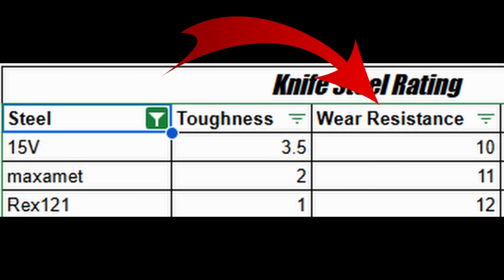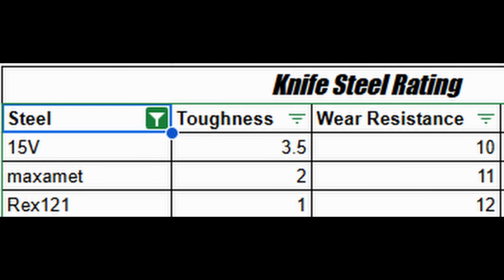Dr. Larrin Thomas doesn't have many steels rated higher for wear resistance than 15V. In fact, according to the charts available on knifesteelnerds.com, there are only 2 steels rated higher for wear resistance than 15V, and that would be by a very small margin. Those steels are Maximet and Rex 121. 15V is rated at a 10, and for comparison, Maximet is rated at 11.